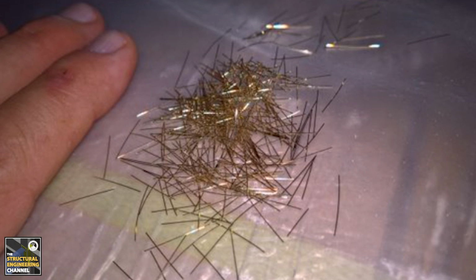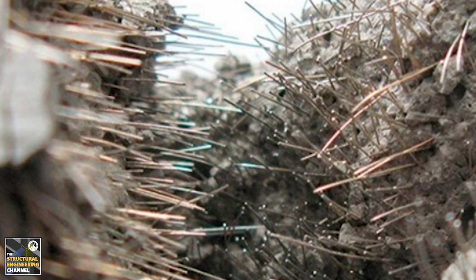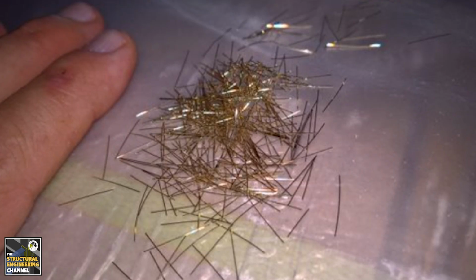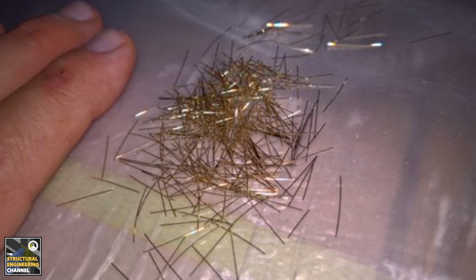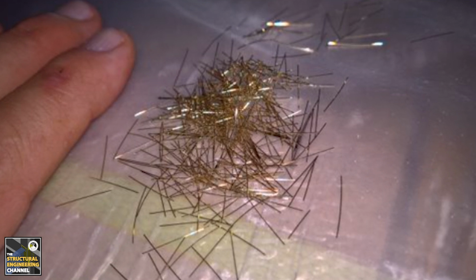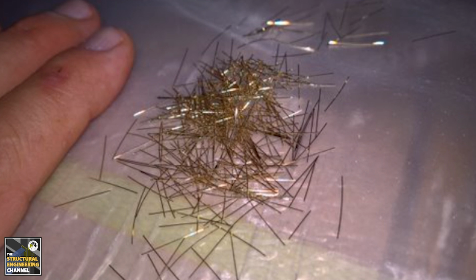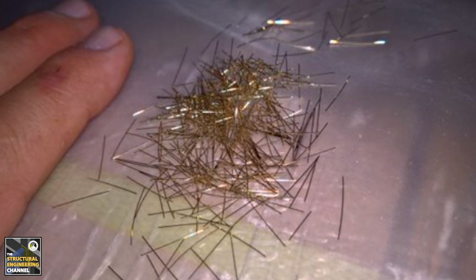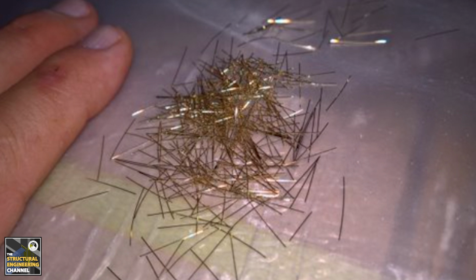And they're not the typical steel fibers that you would use to make fiber reinforced concrete. These fibers are typically just a 1/2 inch long, straight, and they're made from drawn wire, so they're circular in cross section with a diameter of 0.2 millimeters. So a little hazardous to work with, to be honest, because a bunch of little needles you have to be careful with. So those are the obvious differences. UHPC has a lot more cement, which is one of the things that helps give it very high compressive strength.